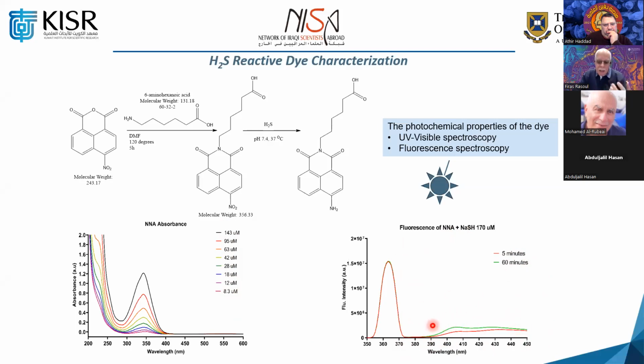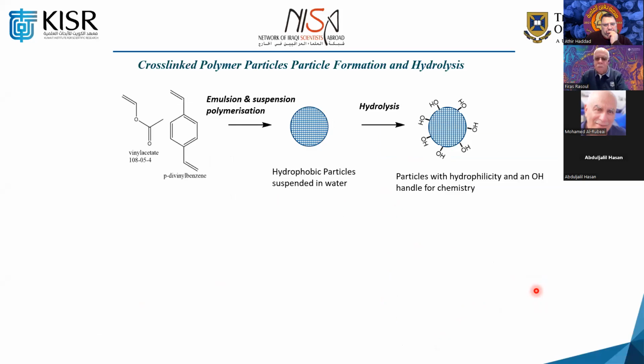I guess this level of emission is relatively good, comparable with the absorption. Here we probably need to normalize it. And if I remove that from the spectrum, then you will be able to see a very broad peak, the fluorescence from this type of molecule. Okay, going back to how to make these